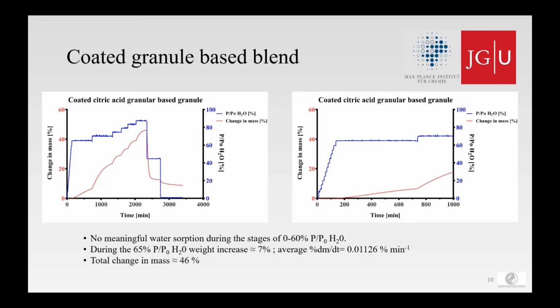And then we come to the coated granule-based blend. Similar to the granule, we have no meaningful water sorption until 60% partial pressure, and also pretty similar during the 65% partial pressure stage. Roughly 7% weight increase took place, and also the rate was roughly similar to the granule that we observed before. Total mass change was relatively the same for all samples, in this case 46%.